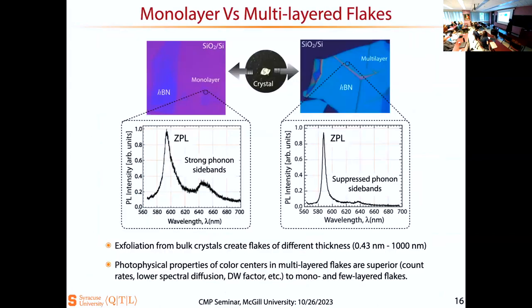I think I showed that from monolayer, we also got a really good single crystal exfoliation. You can clearly see the quality of the resonances. In this measurement, I tried my best to keep the conditions as identical as possible. You can clearly see that for a thick layer, the intensity is much higher, and the coupling to the phonon sideband is much less pronounced, or suppressed, in a multilayer compared to a monolayer. So I always work with really thick-ish flakes.